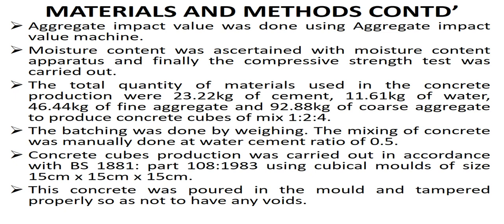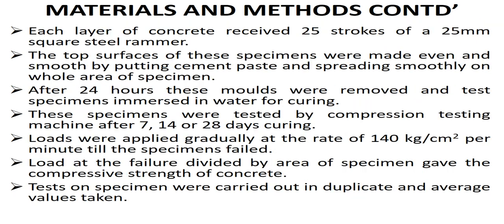This concrete was poured into the mold and tamped properly so as not to have any voids. Each layer of concrete receives 25 strokes of a 25 mm square steel rammer. The top surfaces of these specimens were made even and smooth by putting cement paste and spreading smoothly on the whole area of specimen. After 24 hours, these molds were removed and test specimens immersed in water for curing. These specimens were tested by compression testing machine after 7, 14, and 28 days curing. Loads were applied gradually at the rate of 140 kg per cm square per minute till the specimens failed. Load at the failure divided by area of specimen gave the compressive strength of concrete. Tests on specimen were carried out in duplicate and average values taken.